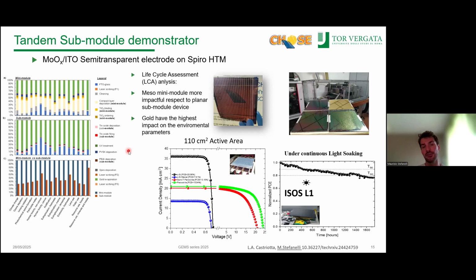we also tried some ITO electrode, in this case on 15 by 15 substrates, in which we fabricated 110 centimeter square active area modules. We tried with gold, with ITO, and we also tried a four terminal tandem configuration with silicon, just as a demonstrator. As you can see, if we use gold, of course, the PCE is around the best PCE that we got also on the other substrate, around 16%. With ITO electrode, we are around 13%. And with the silicon, the module is not really optimized, electro-optically, at that time to get really high efficiency. So practically we got the same efficiency of silicon alone, but it's okay. It was just a demonstrator.